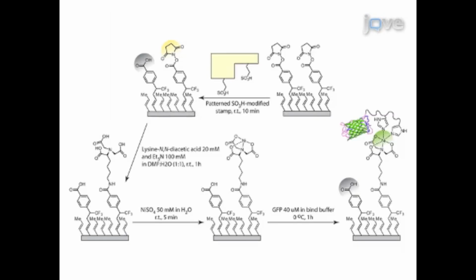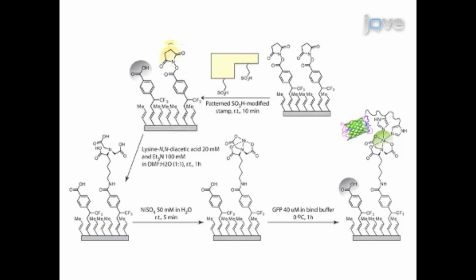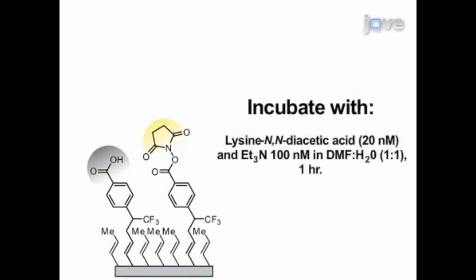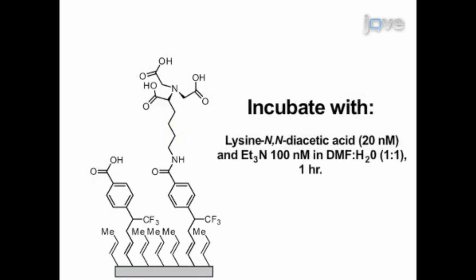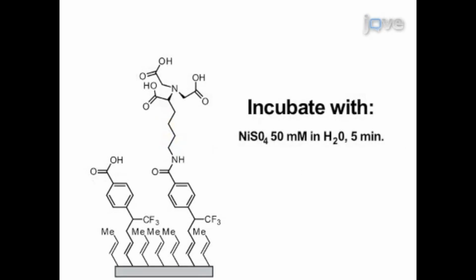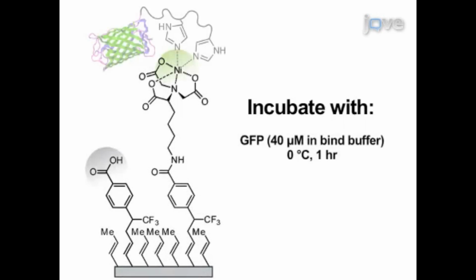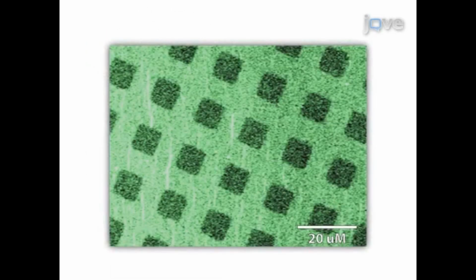Chemoselective functionalization of patterned semiconductors was accomplished by exploiting the differential reactivities of activated and free carboxylic acids. First, nitrilotriacetic acid-terminated heterobifunctional linkers were affixed to the NHS functionalized regions, and the resulting NTA patterned surface was then used as a template for the selective attachment of hexahistidine-tagged GFP. NHS patterned silicon was chemofunctionalized with protein molecules using this approach.